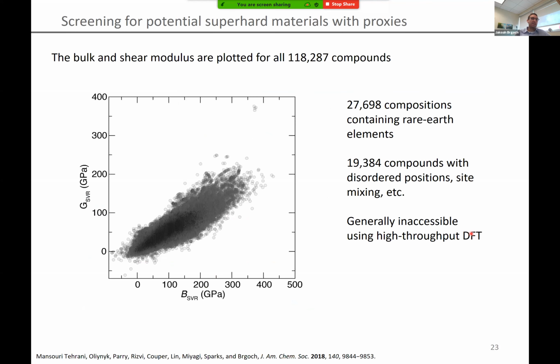Now if we take the 118,000 compounds and plot the bulk versus the shear modulus, here you can see what the data look like. You get a significant amount of data overlap here in the center, in the darker region. It's worth pointing out that we have 27,698 compositions containing rare earth elements, and just under 20,000 compounds with disordered or mixed positions. These are not generally accessible using high throughput calculations, and yet here we are able to access them pretty reliably.